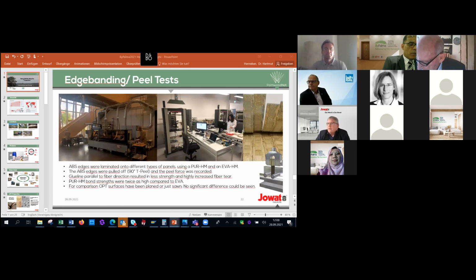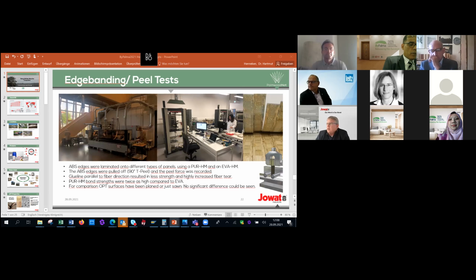Edgebanding. You see the edgebanding machine in our technical center here. And also the tests we did there. There we did no shear testing. We did a peel test, 90 degrees peel test, pulling the edge of the OPT. We used different boards. You can see it here on this example. We have parallel to the fibers on the outside and perpendicular to the fibers in the inside. And you see the image on the picture. You see the vascular bundles actually, you can see them on the adhesive when it's pulled out. And if you're pulling parallel, you're pulling out a lot more fibers.